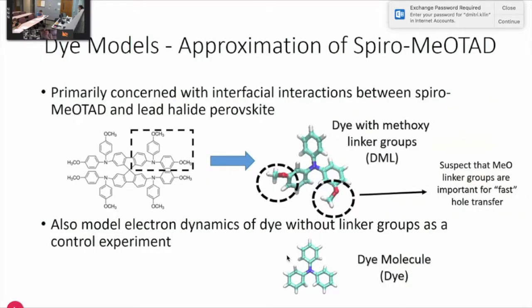For the dye models that we use, a popular hole transfer material in perovskite-based solar cells is spiro-OMeTAD, which is shown to be the most efficient hole transfer material, and it's a rather large organic molecule. So instead of modeling the whole molecule itself, to save computational time, we made an approximation where we only look at a chunk of the spiro-OMeTAD. It's basically like 1/4 of a segment of the entire molecule, which we assume will provide the same interfacial dynamics between the perovskite and the dye molecule. And we also do a control experiment where we look at a dye molecule without the methoxy linker groups to model the through-space charge transfer.